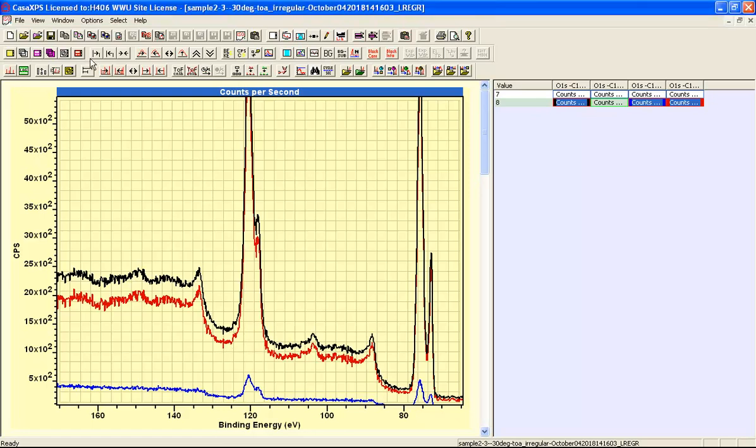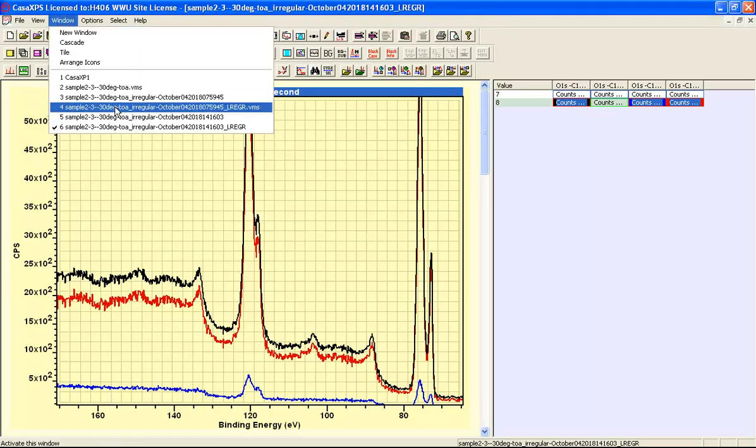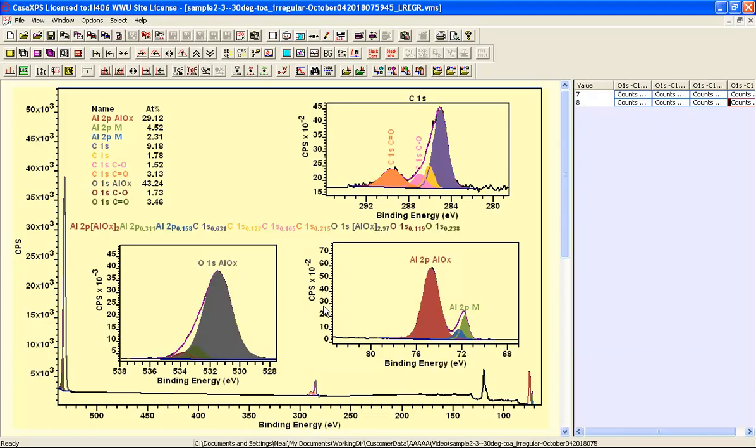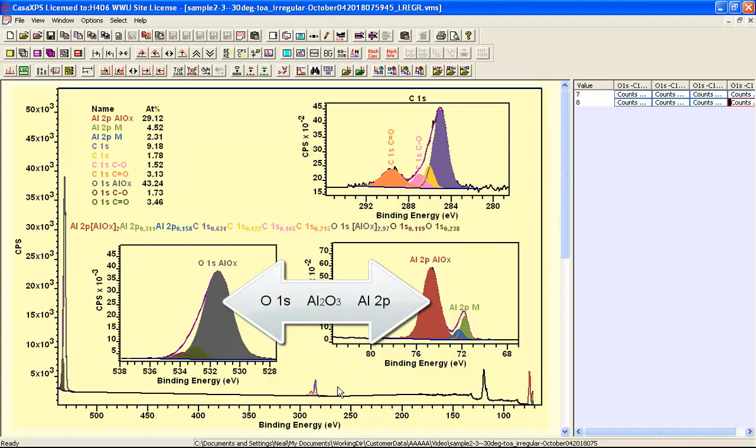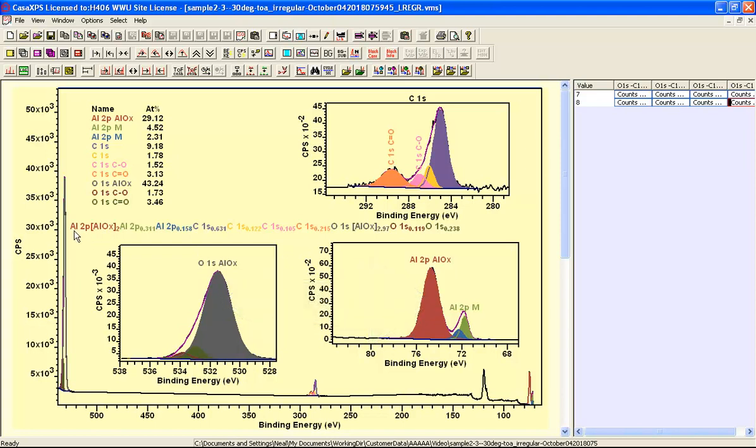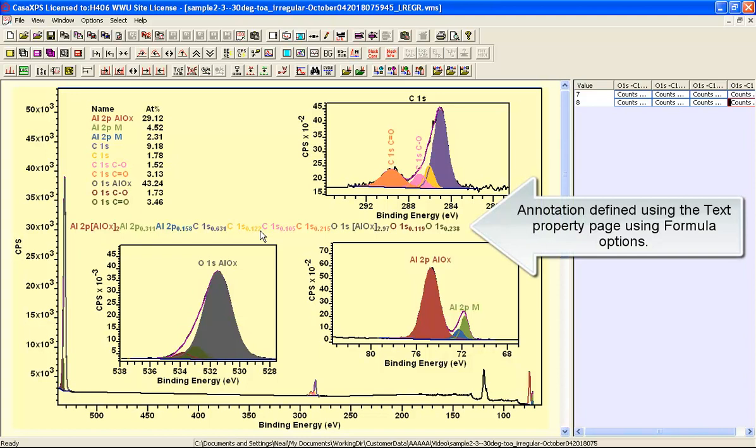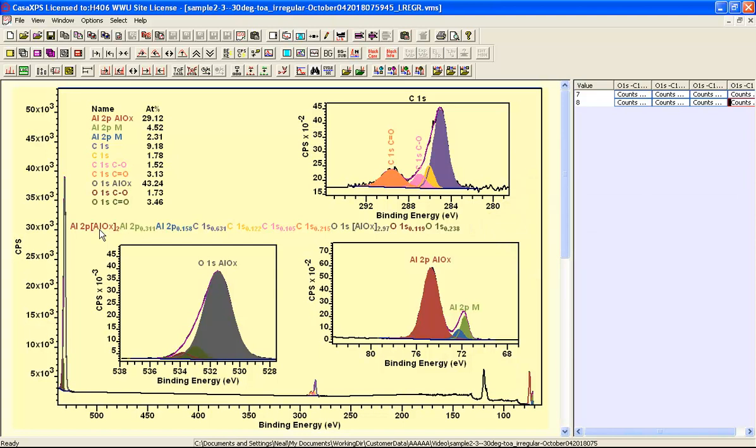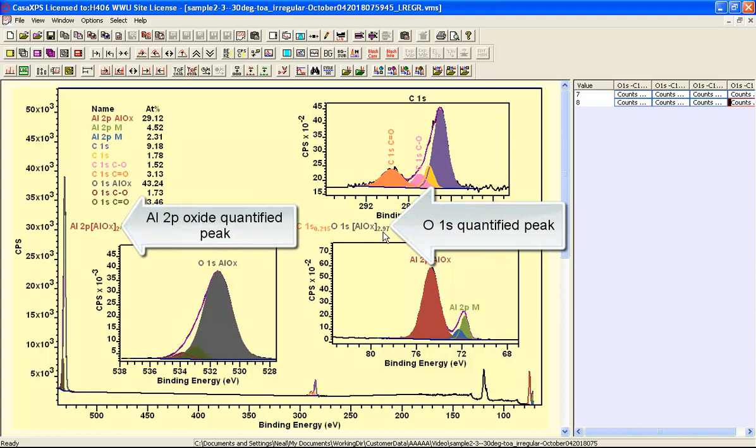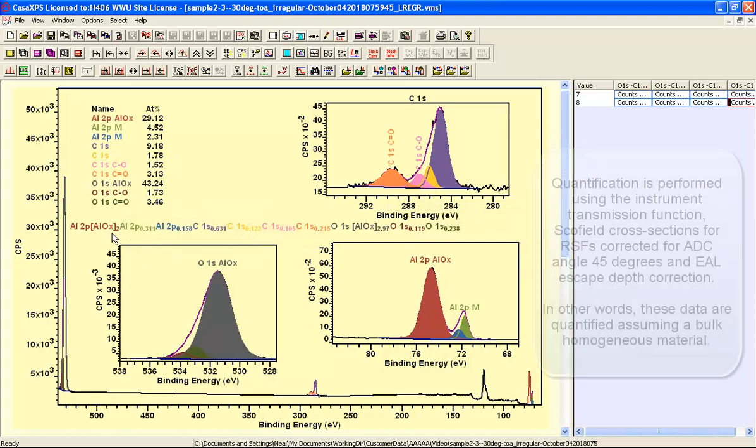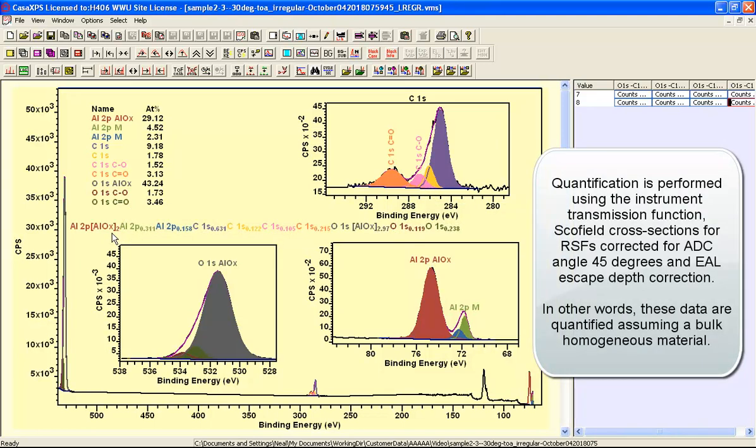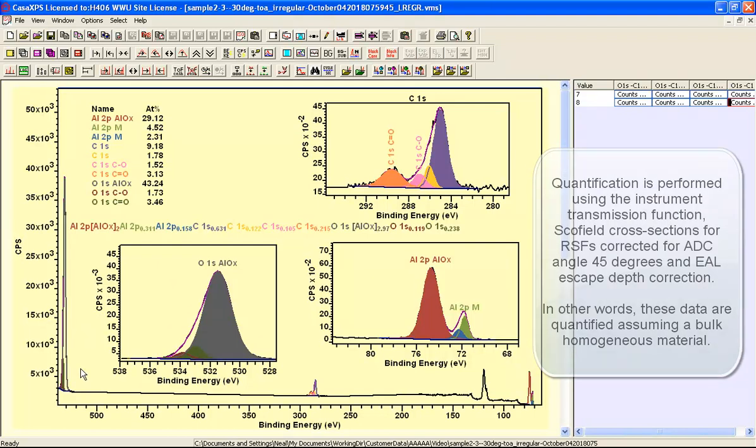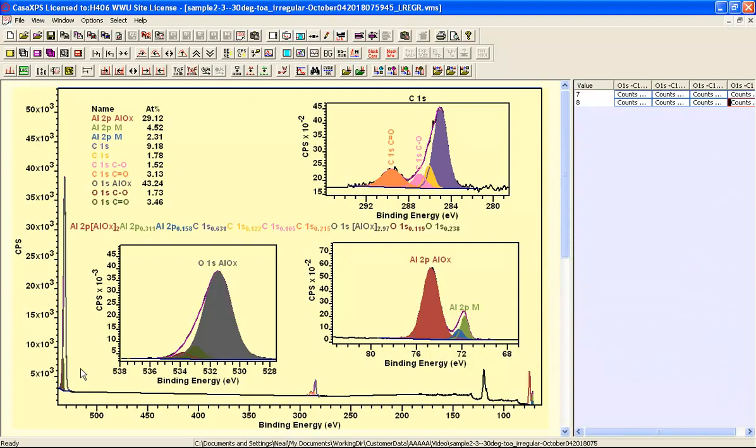So if we now look at a peak model that has been constructed on the component spectrum that includes aluminium oxide from the aluminium 2p and the oxygen 1s, then comparing the ratio of these peaks will give us an indication of whether there's consistency in this theory that this is indeed aluminium oxide at the surface. And when we perform this analysis, and you can see this expression here is giving the ratio of all of these component peaks relative to twice the aluminium 2p that's assigned as aluminium oxide, then the corresponding oxygen peak here is looking close to 3. It certainly has the appearance now of aluminium oxide. And more importantly, the stoichiometry would suggest that this aluminium oxide is very much at the surface. So we can interpret this component as deriving from an aluminium oxide layer at the surface of both of these samples.